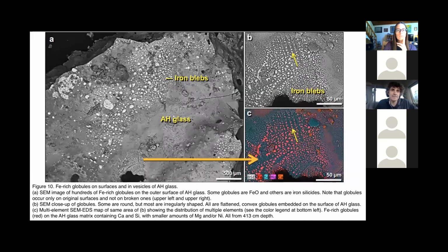One thing, this again reminds me of space weathering, because when you look at some of the dust particles on the moon, you can find a similar kind of feature, these blobs of iron on the surfaces as a result of quenching and cooling, creating these spheres of iron. Of course, there's a different scale. There are large-scale iron blobs and small-scale ones. If you go smaller, it goes almost to the micrometer to nanometer scale. And the composition goes from this iron, silicon, magnesium, calcium composition.